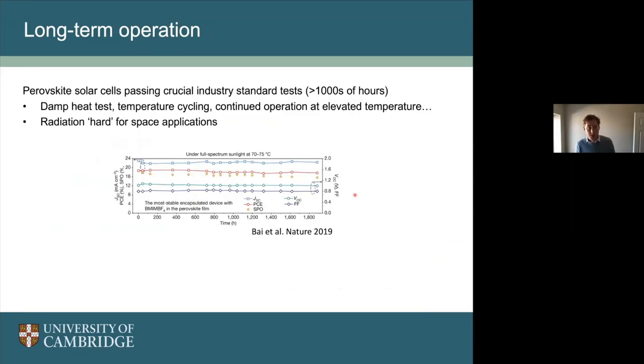And the final thing I wanted to mention was long-term operation. How do we make them last on the rooftop for 30 years plus? They need to pass many industry standard tests, so thousands of hours at very high stress conditions. So we do a lot of tests where we run the cells under these industry standard tests. There's things like the damp heat test where we expose them to very high humidity and very high temperature. So they're at something like 85% humidity and 85 degrees Celsius for some time, and we operate them and we see how long they can last under those conditions.